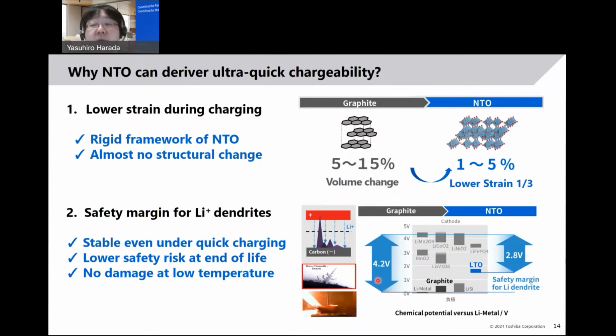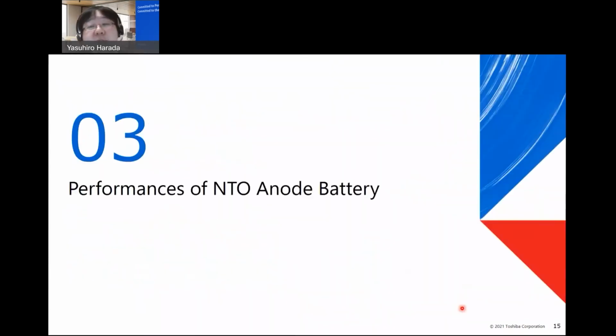The graphite anode is very close to the lithium metal formation potential, and it has a very high output voltage, but there is a possibility that lithium metal dendrite could be formed in the electrode under quick charging cycles or low temperature conditions. This may cause an internal short circuit and a battery explosion. NTO battery has almost no worries about lithium dendrite, even under extreme conditions. That's why we are committed to the NTO anode. Even if the output voltage is lower than graphite, we have the safety margin against lithium dendrite formation. Here, I will show you the NTO battery performances and what NTO battery can do.